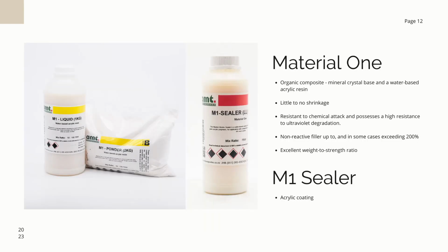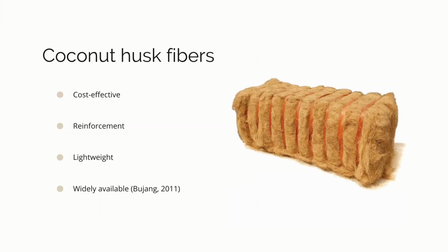The resin that was used is the AMT Solutions Material 1 resin. This resin was designated for the prototyping as it is an organic composite material that consists of a mineral crystal base and a water-based acrylic resin. This resin has beneficial characteristics such as low shrinkage during curing, resistance to chemical and ultraviolet degradation, and an excellent weight-to-strength ratio. The resin also lends itself particularly well to the use in combination with filler material. The resin surface is coated with Material 1 Sealer, which is an acrylic coating that improves impact resistance, surface quality, and resistance to water. The next material used was coconut husks.